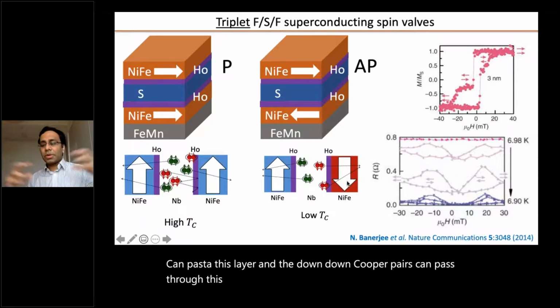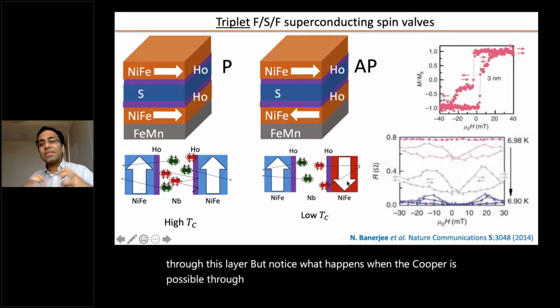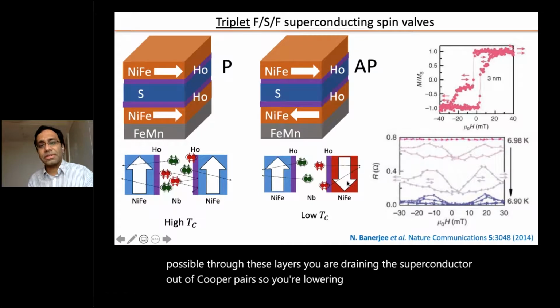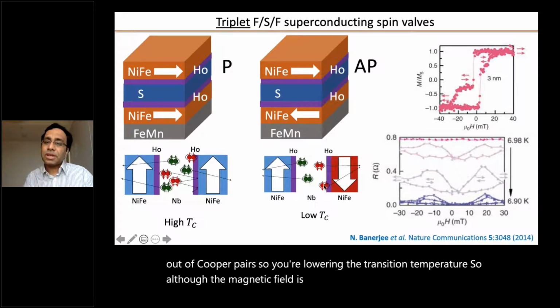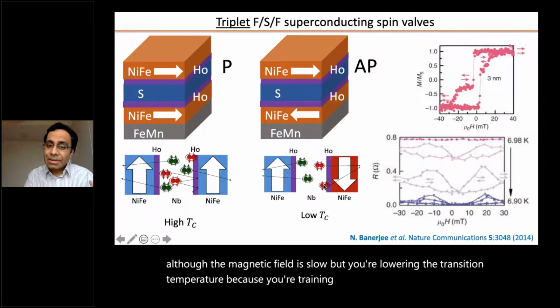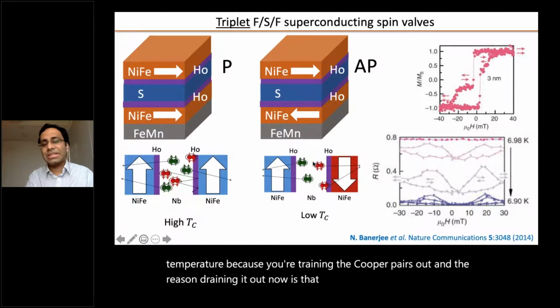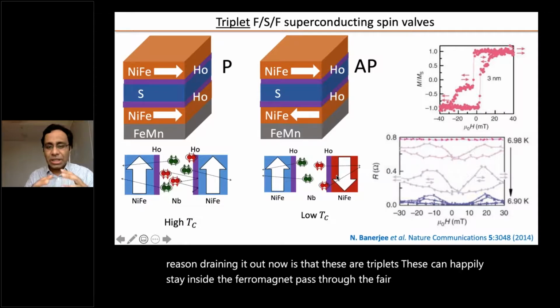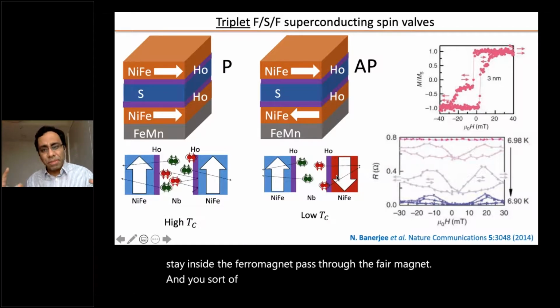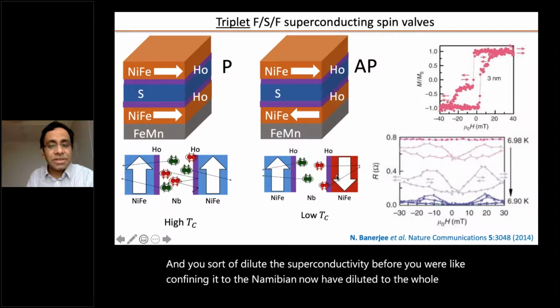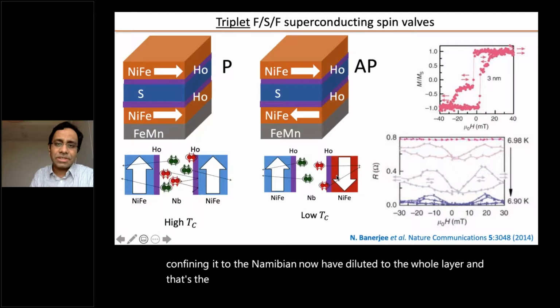But notice what happens when the Cooper pairs are passing through these layers. You're draining the superconductor of Cooper pairs, so you're lowering the transition temperature. Although the magnetic field is low, you're lowering the transition temperature because you're draining the Cooper pairs out. And the reason you're draining them out now is that these are triplets. These can happily stay inside the ferromagnet, pass through the ferromagnet, and you dilute the superconductivity. Before, you were confining it to the niobium, now you have diluted it to the whole layer. And that's the reason that the transition temperature changes.